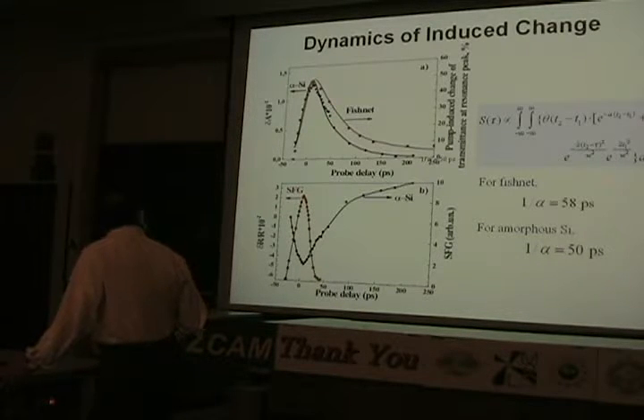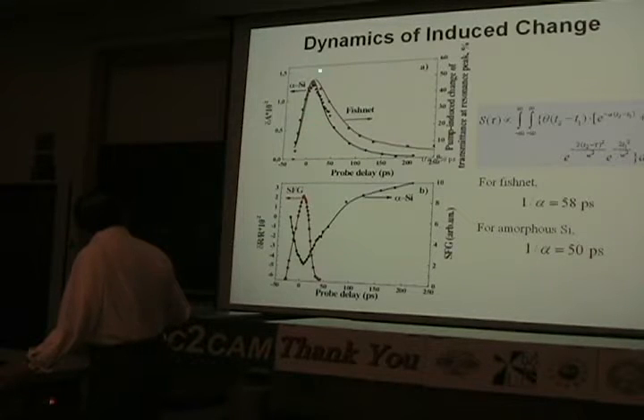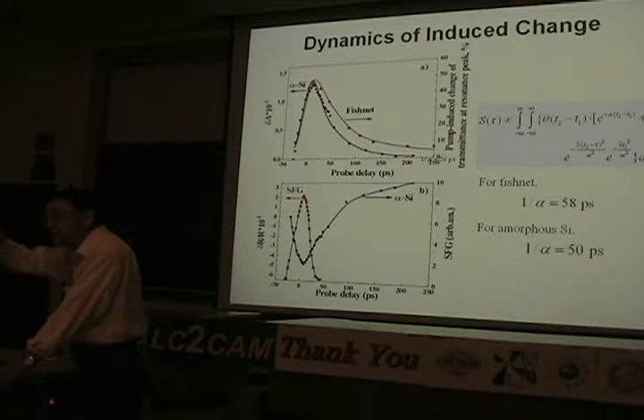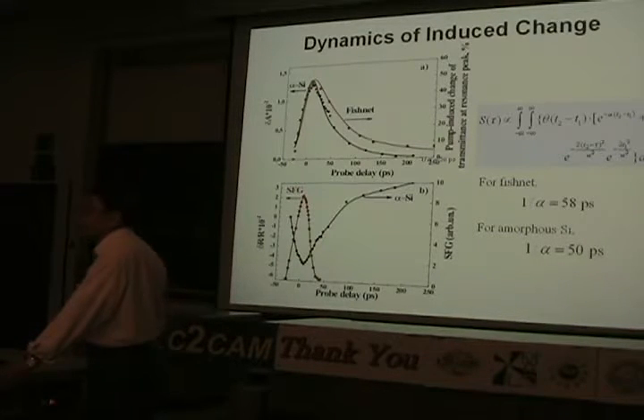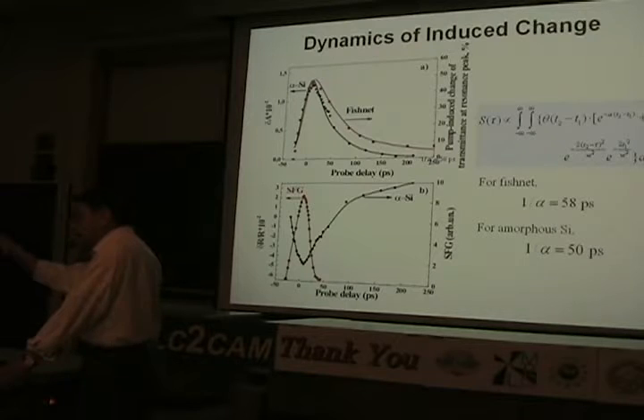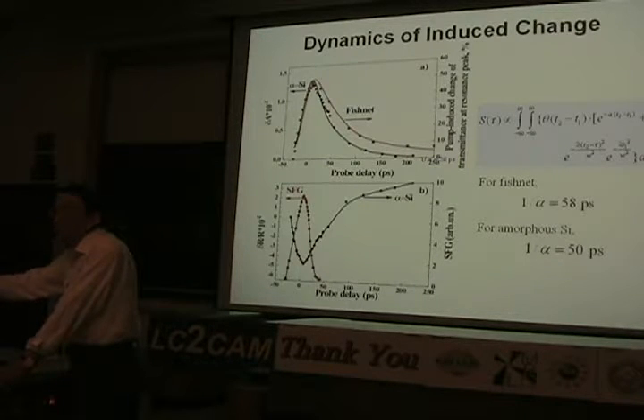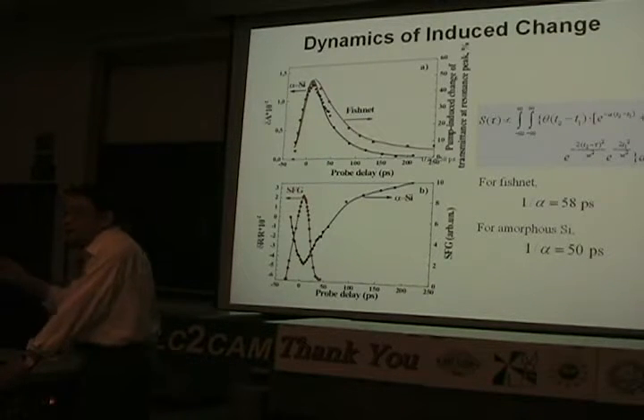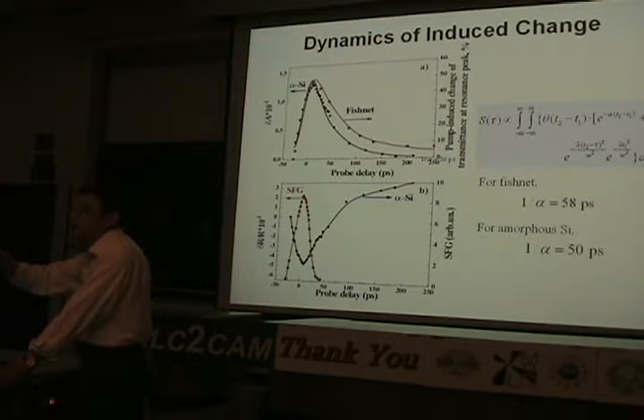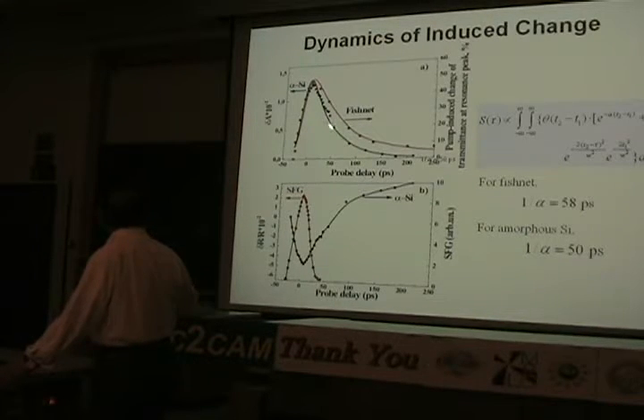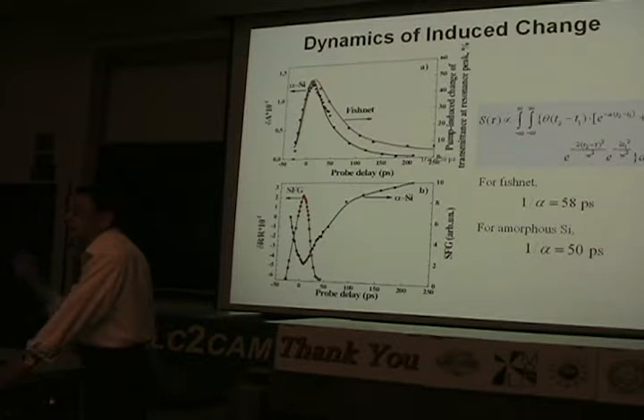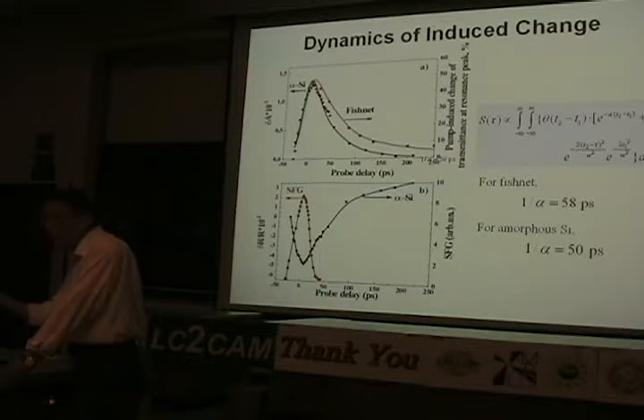And why do I say that? Because the red curve is the time-resolved measurement on the fishnet. The black curve is the induced absorption on a film of amorphous silicon only. And so you can see the induced absorption in the amorphous silicon has more or less the same decay curve as the fishnet. So it indicates the mechanism is indeed the carrier excitation and relaxation.